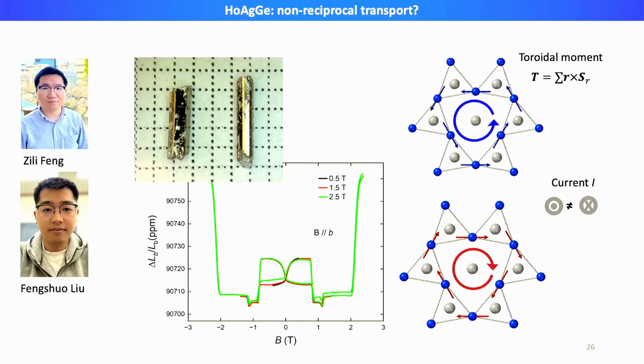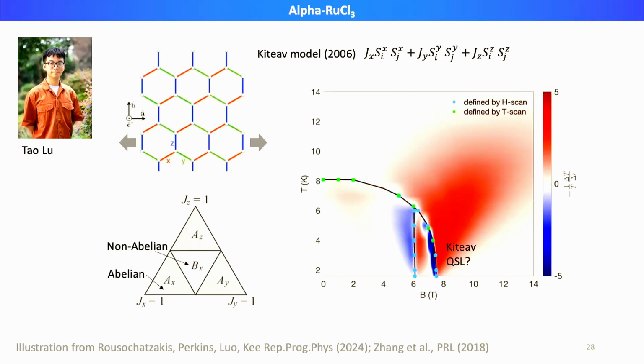Other questions, Jason? Can I ask about ruthenium chloride? Yes. Very interesting data. What field orientation is it, and have you thought about probing different field orientations? Yeah, that's a great question. The magnetic field is applied in the ab plane, and in particular, I believe this is along the a-axis, perpendicular to the bonds. We did apply the magnetic field along the other axis, and we see a much weaker divergence of the signal there. We haven't fully understood this, but my understanding is that it's also related to the Kitaev interactions.